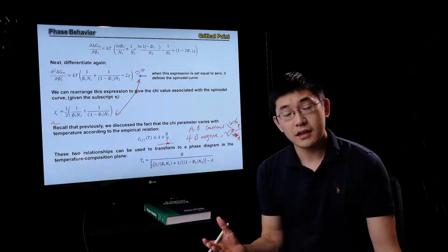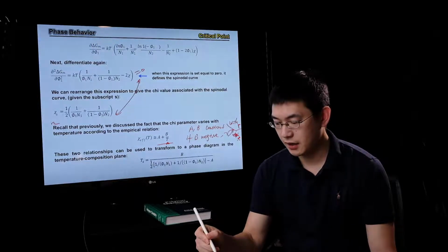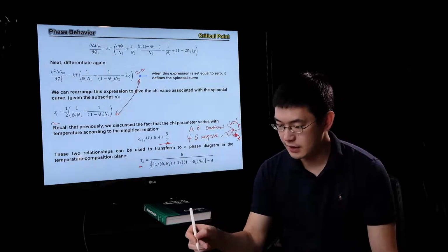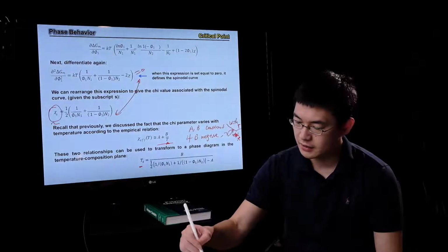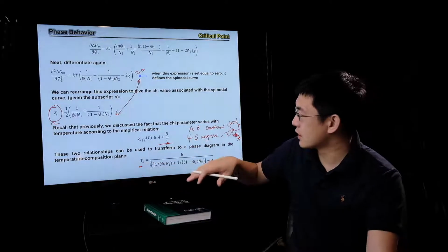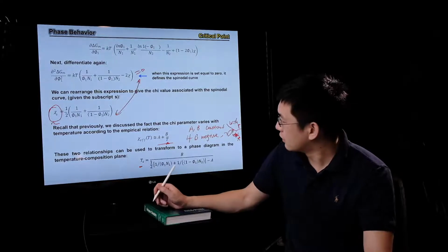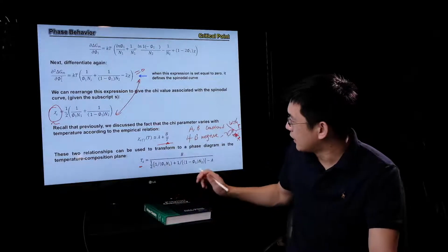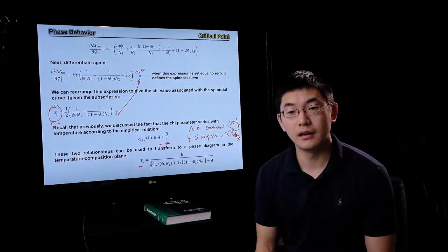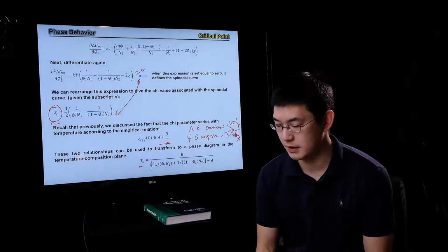So if we get a value of this particular equation, we can back calculate what Ts is. Ts is the critical temperature, and there's nothing fancy. We just applied chi into this particular equation, and this is what you would get for Ts. And Ts here is the definition of critical temperature. If we know what phi is, what N1 is, and you know the constants A and B, you can know the critical temperature at which your system will behave as a mixed or non-mixed phase.